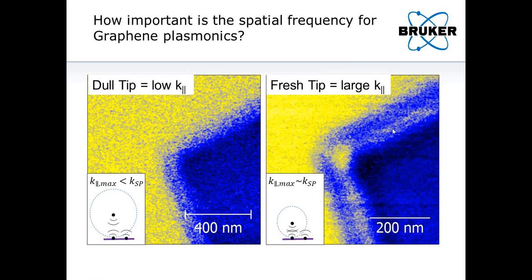The fresh tip image is clearly showing the graphene plasmon, whereas the dull tip image looks very blurry. That's because it's simply not able to launch these waves. It does not have the necessary spatial frequency.